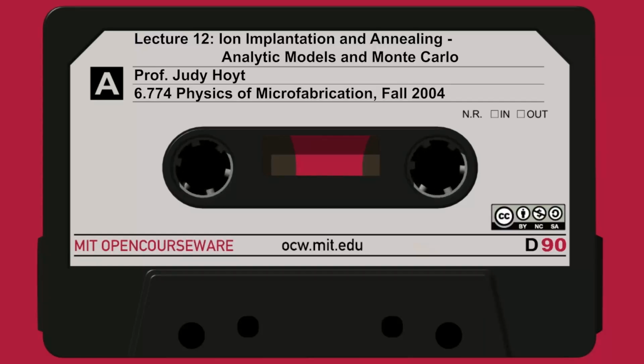So here's boron. Again, you can see boron goes very far. So if I'm at an energy of, say, 80 kilovolts, and I have boron, the projected range is a quarter micron. That's 0.25. For arsenic, at that same energy, it's about 0.05 microns, or about 500 angstroms. So it's much, much shallower.